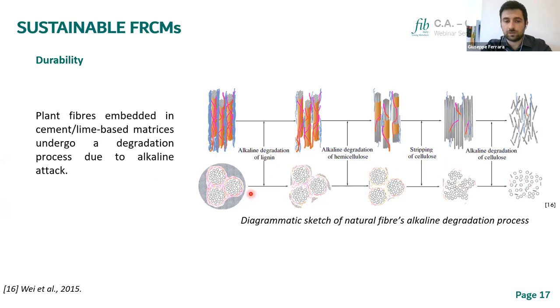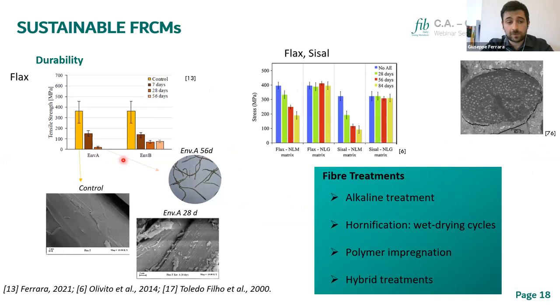Well, when we put this kind of fibers in an alkaline environment, such as that of a cement or lime-based matrix, we have at first the degradation of the lignin, the external part. This degradation proceeds and advances inward within the filaments up to the degradation of the cellulose. In this case, we have a complete degradation of the materials. We have several experimental evidences of this aspect, in which, for example, by aging flax fibers in cement-based or lime-based materials, we have a complete degradation of the fibers. There are also other studies showing that this degradation is particularly severe with lime-based mortar, and by sometimes modifying the mortar, we can somehow improve this aspect. We also have some problems at the interface between fibers and matrix due to the volume variation of the fibers caused by water absorption.